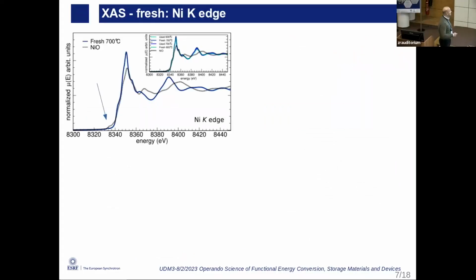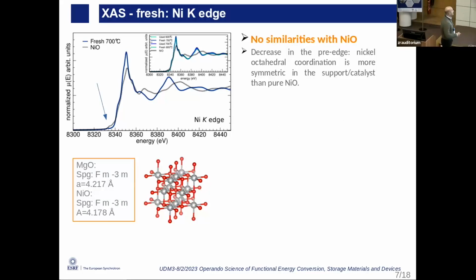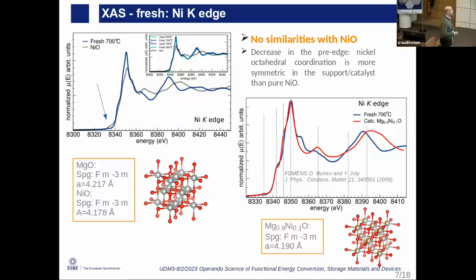So then, let's go to the results. From the nickel point of view, it's clear from the XANES that there is no nickel oxide, and this suggests that the nickel goes inside the structure to make a solid oxide solution with the magnesium oxide. To confirm this, we did a simulation with a DFT-based code like FDMNES to reproduce the structure, since XANES is sensitive to the multiple scattering pattern, and so to the three-dimensionality of the material. We could reproduce quite nicely basically all the features except one. So this strongly suggests that the nickel goes inside and creates this mixed oxide solution.